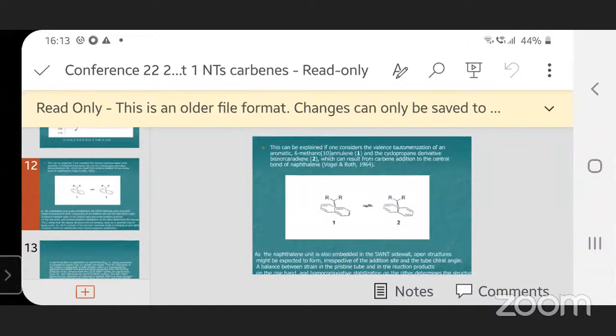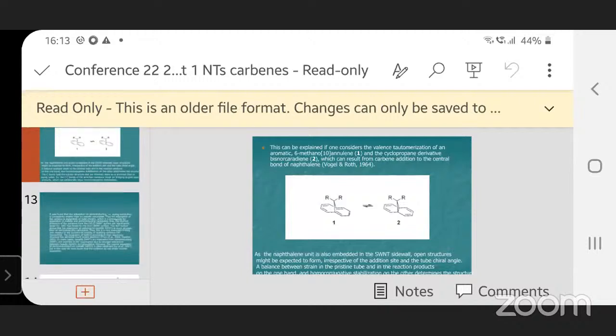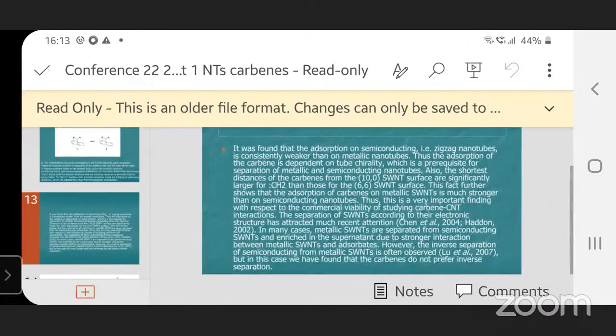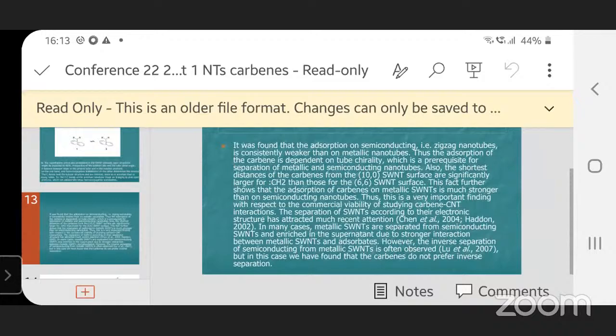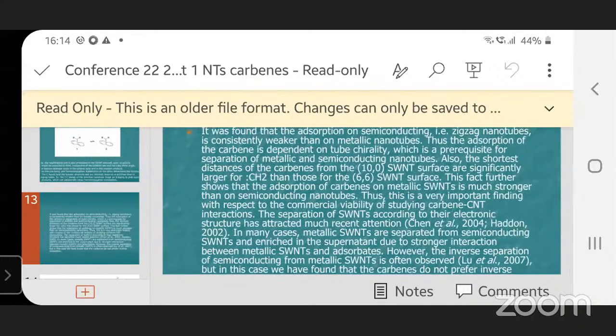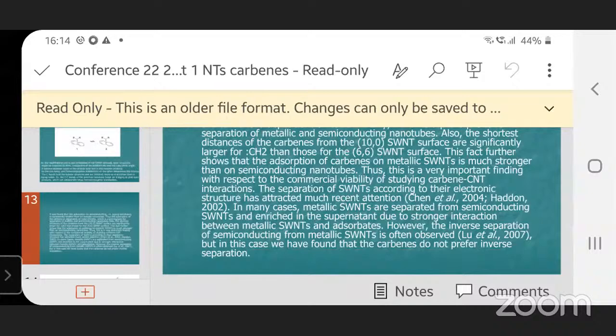We tried to explain this with the reasons given in the literature, and it was found that the adsorption on semiconducting, that is zigzag nanotubes, was consistently weaker than on metallic nanotubes. Thus, the adsorption of the carbene is dependent on tube chirality. This is very important: we predicted that the adsorption of the carbene is dependent not on the carbene, but on the tube chirality, which is a prerequisite for separation of metallic and semiconducting nanotubes. And the shortest distance of the carbene from the 10-0 SWNT surface is significantly larger for CH2 than for the 6-6 SWNT surface. So adsorption of carbenes on metallic SWNTs is much stronger than on semiconducting nanotubes.